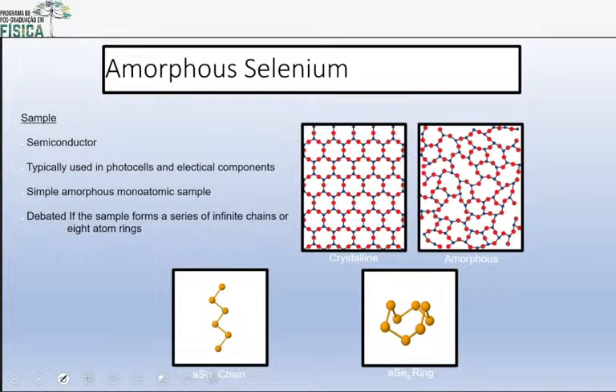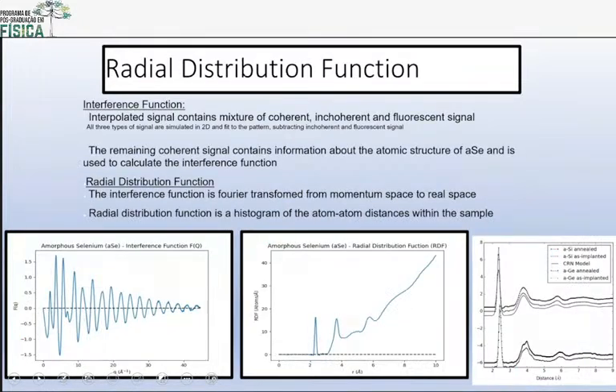So selenium is something we did. It's a very interesting amorphous material. The big question was: is it made up of chains or rings? Chains or rings? I know. And we measured the sample. Very, very nice pattern. Look at the quality of the radial distribution function.